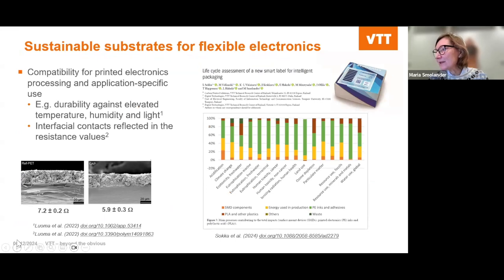And in the same project, we then investigated the LCA of the smart label, which was our example case in this project. It's a smart label for temperature monitoring during the logistic chain. And what could be seen in this LCA study was that most of the environmental load in this case comes from the printed electronic inks, the conductive inks and adhesives. It is this green bar here. The yellow one is the energy used in production, so that is also quite considerable. And then some parameters are also contributed quite a bit by the substrate material that is used.